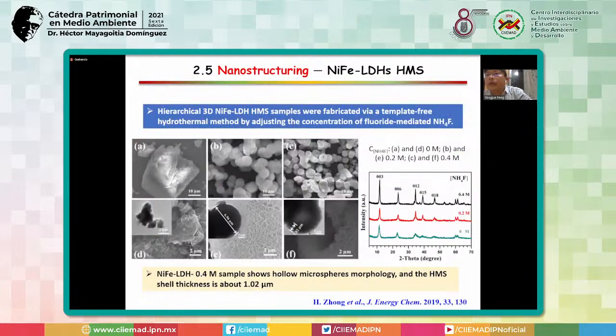And also we can make nanostructured nickel iron LDH as hollow microspheres. We can fabricate them by a template-free hydrothermal method by adjusting the concentration of fluoride. That means we get the hollow sphere of LDH. As we know, the LDH is generally a nanoplate structure. It's difficult to get the sphere. Here we just show the 0.4 molar. It shows very hollow microspheres, and the shell thickness is about 1.02 micrometer. So we test it for the oxygen evolution.